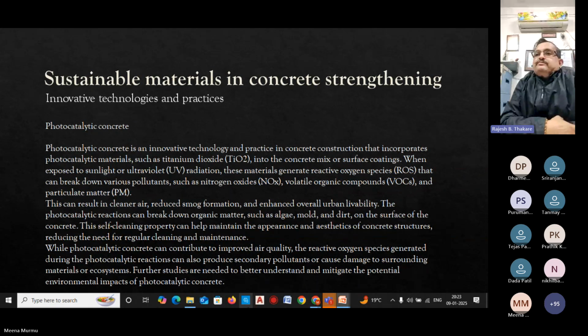Another technology which we can use is photocatalytic concrete. Photocatalytic concrete is an innovative technology and practice in concrete construction that incorporates photocatalytic materials such as titanium dioxide into the concrete mix or surface coating. When exposed to sunlight or ultraviolet radiation, these materials generate reactive oxygen species that can break down various pollutants such as nitrogen oxide, different volatile organic compounds and particulate matter. This can result in cleaner air, reduced smog formation, and enhanced overall urban livability.